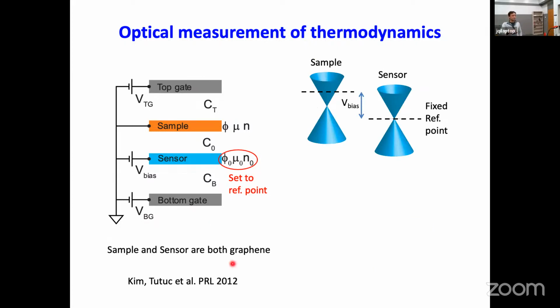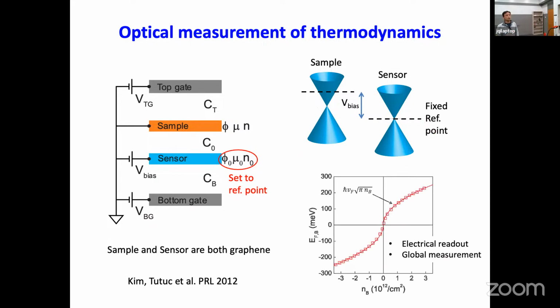Emmanuel Tutuc's group published a paper, PRL 2012, that first realized you can use this method to read out the chemical potential. In their experiment, they use a graphene sensor to read out a graphene sample. A natural reference point for the graphene sensor would be to put the Fermi energy exactly at the Dirac point, and you can monitor that by just measuring the resistance of the sensor. So it's actually a global measurement, because it's an electrical measurement through this entire sensor layer to read out the chemical potential from the sample.